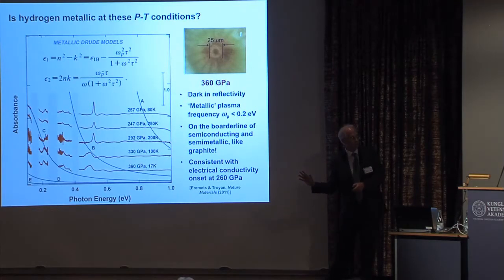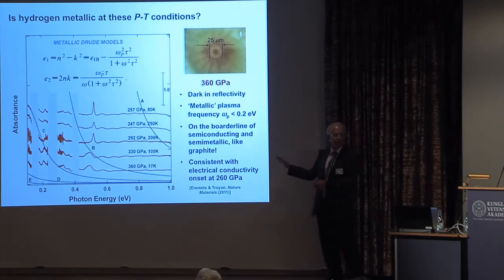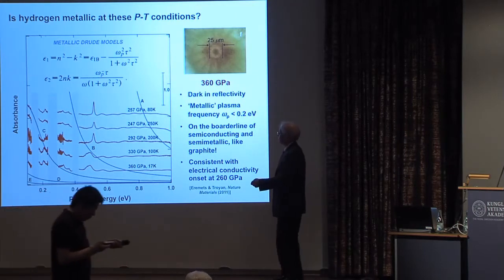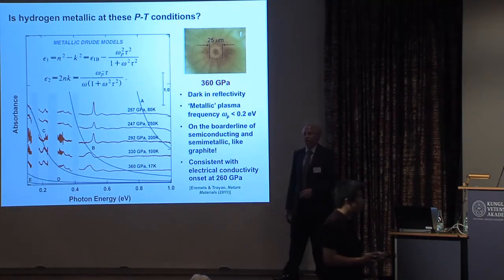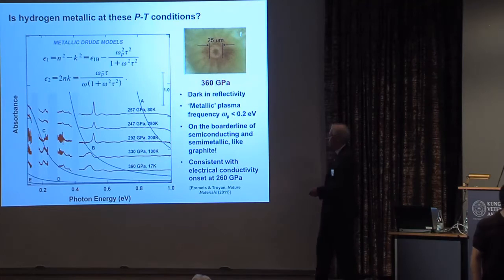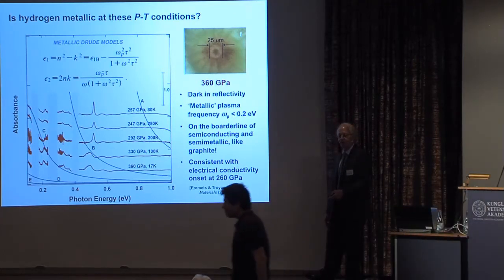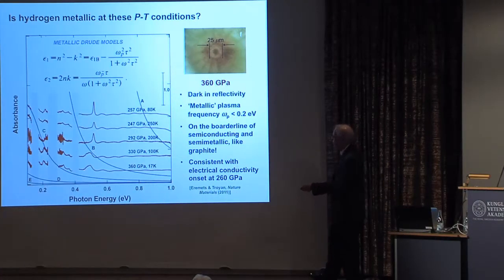You can do two photon absorption, but the intensity of the synchrotron source is not high enough for two photon activity. The bottom line is, this is consistent with a semi-metallic state, rather like what you have in the case of graphite. And the magnitude of the upturn in reflectivity and absorption is consistent with electrical conductivity measurements that have been carried out.